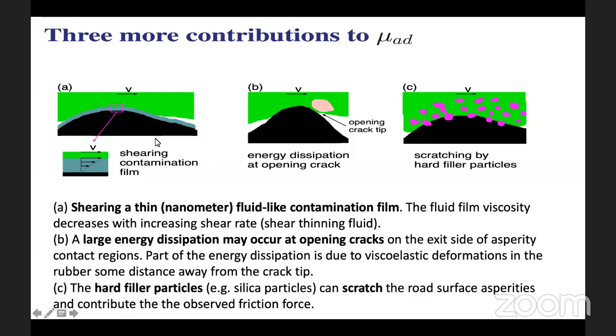At the area of real contact, you can shear a thin film, which is a contamination film. Here in this figure there is a contamination film. You can shear this film, and there is energy dissipation here. If you consider the asperity and the rubber, if you move the rubber over an asperity, then you have some cracks at the edges, and when those cracks open up, they release energy, and that can also contribute to the overall frictional force and the resultant adhesive friction coefficient.